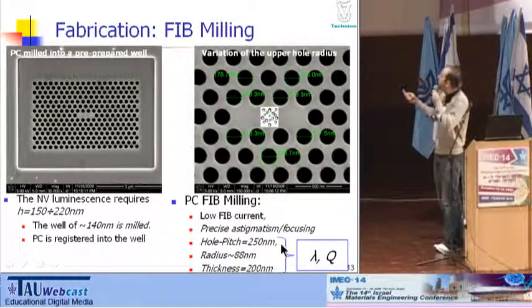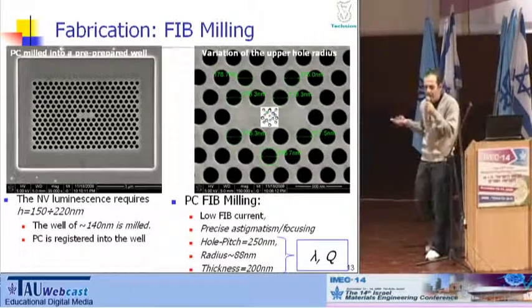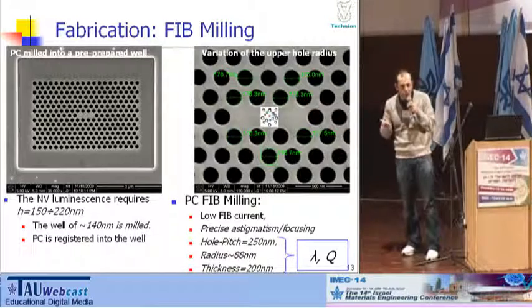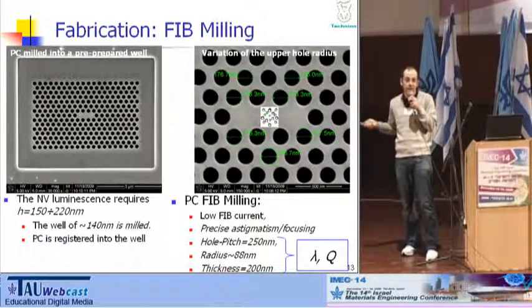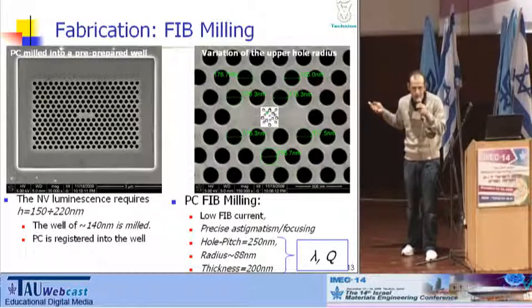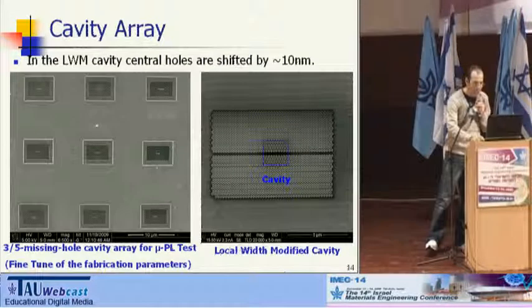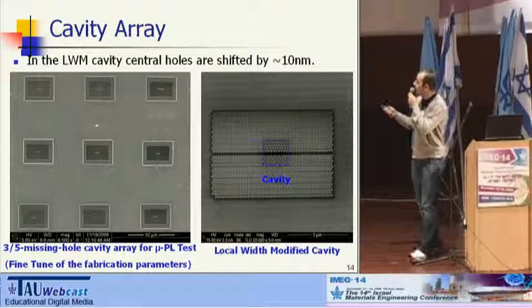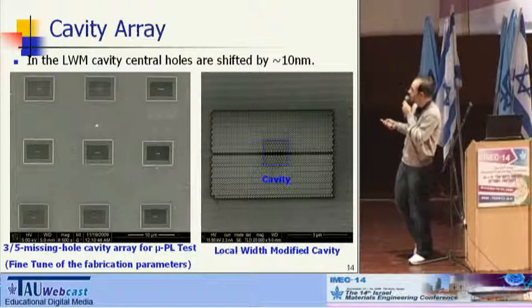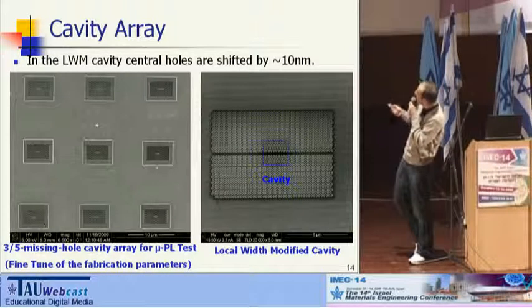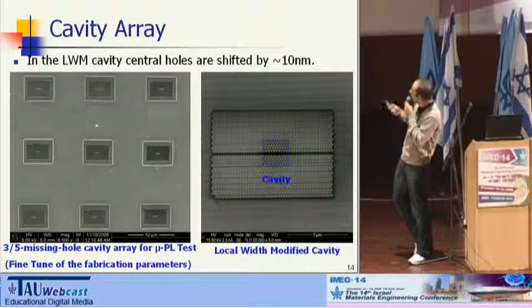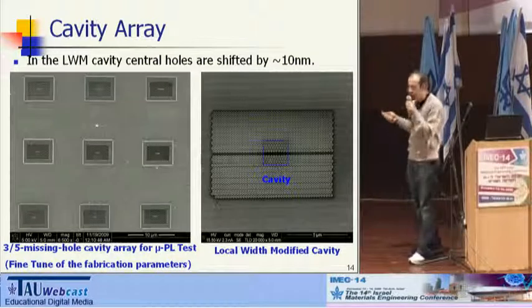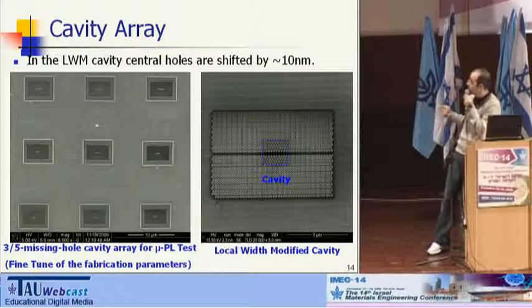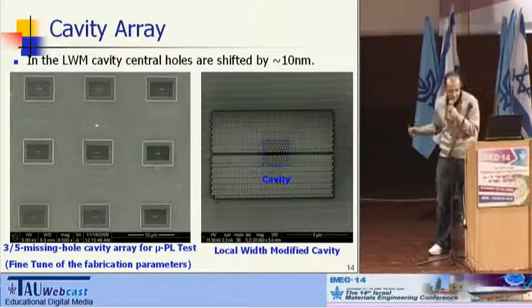Certainly, inside, we would like to position a single NV center, but since it is a yellow diamond, it is full of NV centers, and this job was done for us before. So, now, we have produced an array of photonic crystal cavities with different designs, and this one is an ultra-high Q nanocavity with a photonic waveguide inside and holes shifted by several nanometers. Both of these were not characterized optically yet.